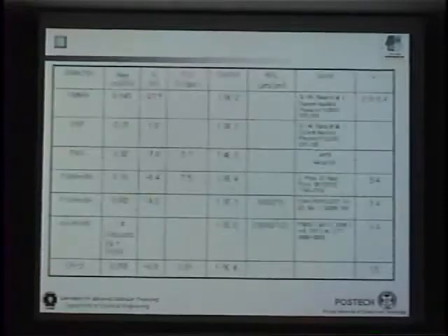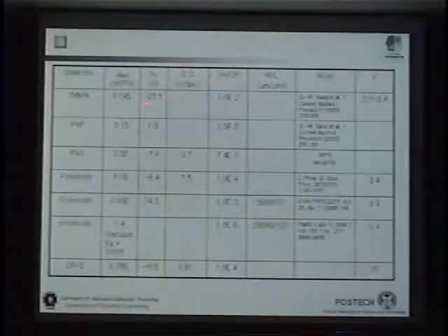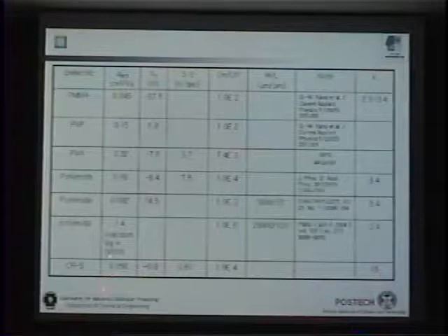Next slide. So these are the values reported in the literature for different gate dielectrics, the mobility, threshold voltage, and other transistor parameters. And we would like to stress that the CRS film with a K value of about 15 shows very low threshold voltage, comparable mobilities, and the on-off ratio is quite acceptable too. Next slide.